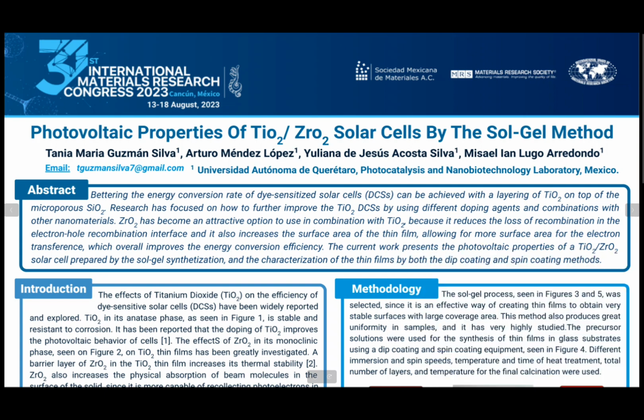The abstract reads, bettering the energy conversion rate of dye-sensitized solar cells, or DSSCs, can be achieved with a layering of titanium dioxide on top of the microporous silicon dioxide. Research has focused on how to further improve the titanium dioxide dye-sensitized solar cells by using different doping agents and combinations with other nanomaterials. Zirconium dioxide has become an attractive option to use in combination with titanium dioxide because it reduces the loss of recombination in the electron-hole recombination interface, and it also increases the surface area of the thin film, allowing for more surface area for the electron transference, which overall improves the energy conversion efficiency.